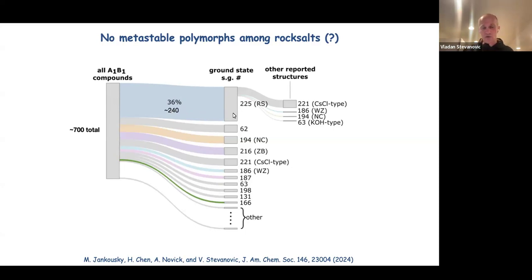So this is the statistics. Out of 700, 240 goes to space group 225, and this is the distribution of the other crystal structures. If you then focus on these and start looking for reports of metastable polymorphs, for the majority of the 240 you find nothing. And for a smaller subset, you find only 4 crystal structures that have ever been reported in addition to rock salt: the cesium chloride type, the wurtzite, the nickeline, so nickel arsenide, and this potassium hydroxide. And it is known from experiments that these 4 will all transform quickly into rock salt. So cesium chloride is a known high pressure phase of rock salt.